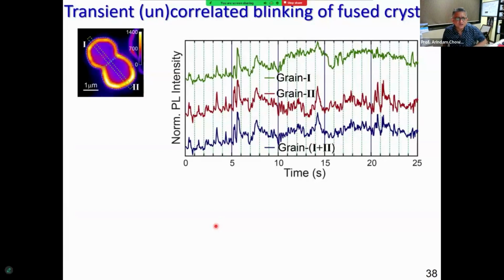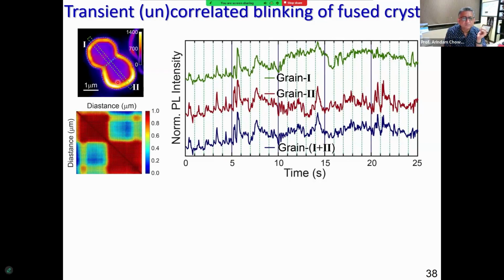This is a situation where we have two fused grains, 1 and 2. And if you look at these two fused grains, and if I plot the correlation map, you see clearly that each fused grain shows highly correlated behavior. Can everybody see this? I hope they can. But not the 1 plus 2 together.